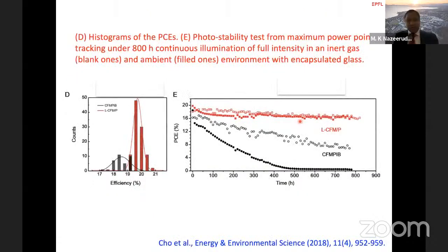Now, the beauty of depositing the two-dimensional perovskite on the three-dimensional perovskite is shown here. The open lines are measured under argon atmosphere, the long-term stability of these perovskite solar cells up to 800 hours. And the solid lines are encapsulated but measured under outside atmosphere conditions. However, under similar conditions, the reference sample measured under argon atmosphere, that's open circles, and measured under normal air conditions with encapsulation, the stability is decreasing significantly compared to the layer by layer deposition. So the take-home message is that layer by layer deposition enhances the perovskite stability significantly.